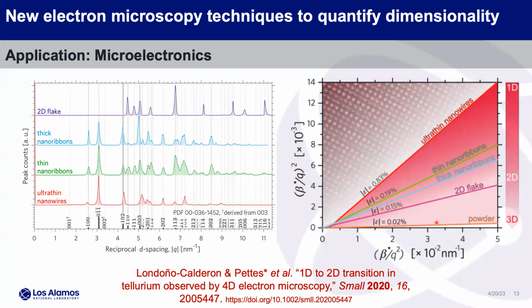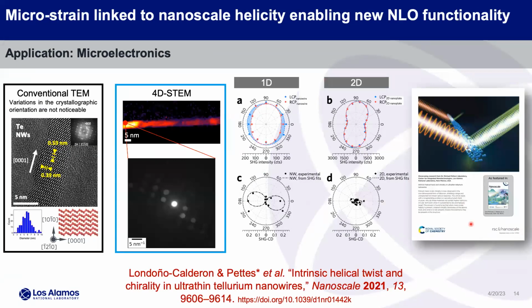But it trends from 1D to 2D to 3D, which means there should be some local relaxation in the 1D material to accommodate that built-in strain. And so that brings us to circularly polarized light. When you have helicity in the material, there should be a degree of circular polarization.